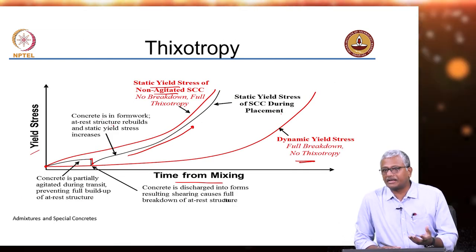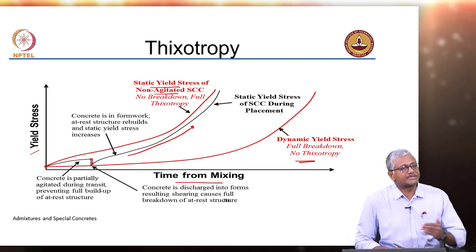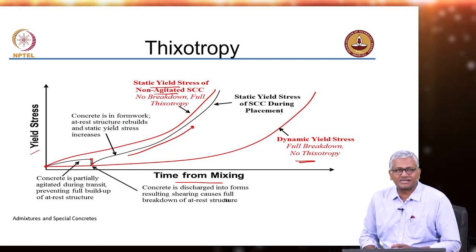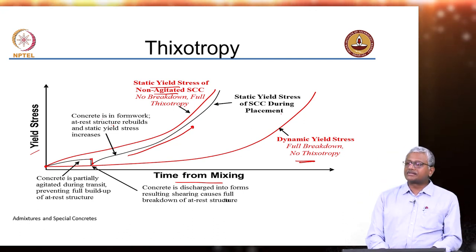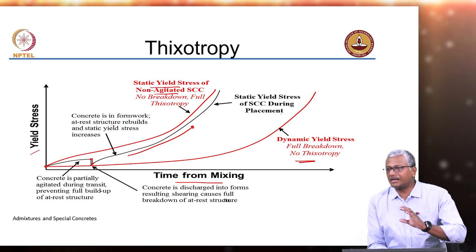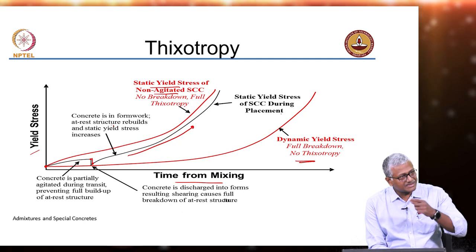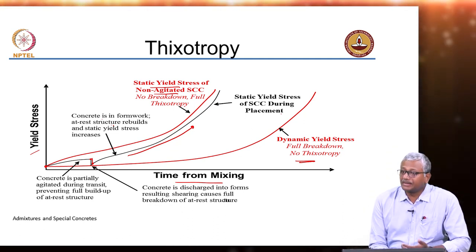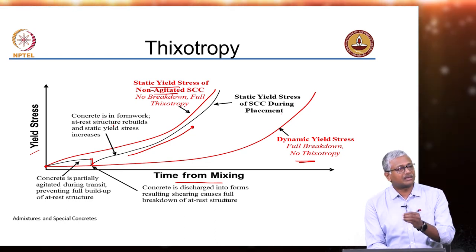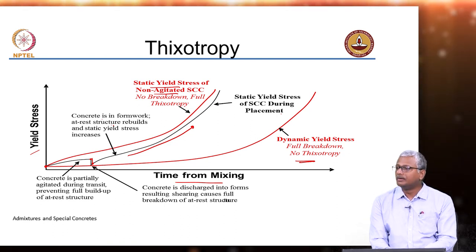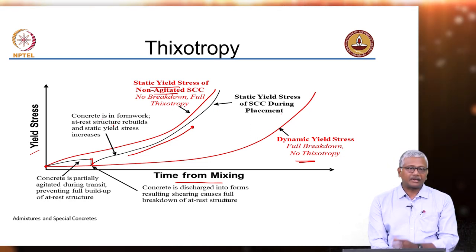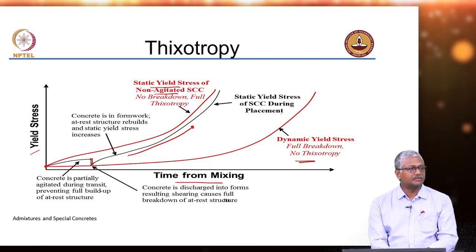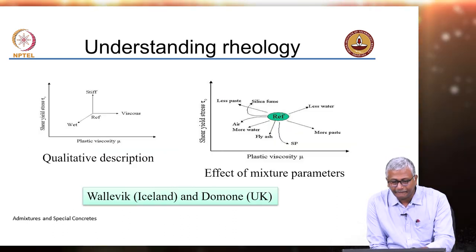Thixotropy affects the build-up of internal stresses as concrete is transported from the plant to the job site, which is very important for understanding slump loss over time. In North America, an approach called the 'Verifi approach' allows assessment of slump and fresh concrete properties inside the truck as concrete is delivered, which correlates well with the fresh properties needed at discharge. This system is used to actively control the rheological properties. Understanding rheological control will become clearer when we discuss self-compacting concrete and 3D printed concrete.